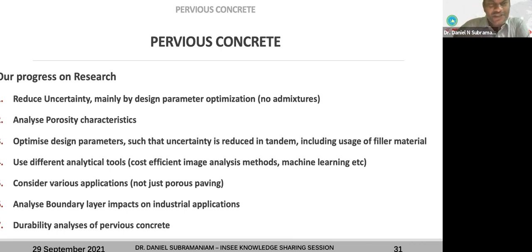I have looked at reducing the uncertainty mainly by design parameter optimization. I don't want to get into admixtures and things like that. One of the tools that I used is using the proper aggregate size and a degree of compaction that can induce some kind of uniformity in pervious concrete without compromising the permeability itself. And then we analyze the pore characteristics, porosity characteristics, and optimize design parameters such that uncertainty is reduced in tandem, including usage of filler materials.